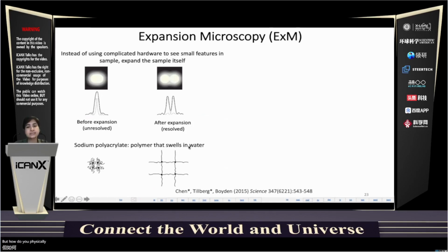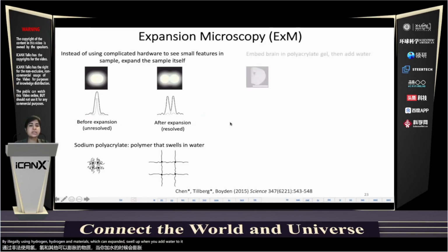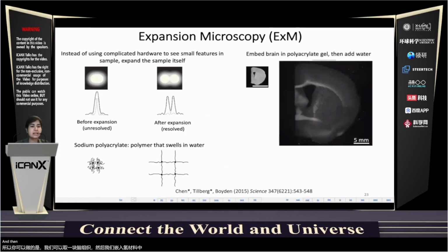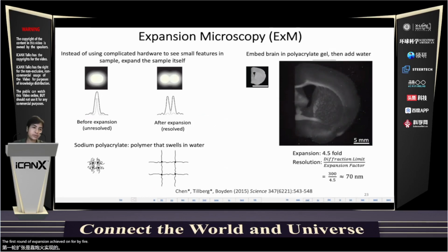But how do we physically expand a sample? You can do that by using hydrogels. Hydrogels are materials which can expand and swell up when you add water to them. So we can take a piece of brain tissue, embed it in the hydrogel material, and then just add water. The brain tissue expands along with the hydrogel. What you're seeing in the image is the same tissue before and after expansion. In the first round of expansion, we achieved around a 4.5-fold expansion factor. That means if the diffraction limit of the microscope is 300 nanometers, by 4.5-fold expansion we can get around 60 to 70 nanometer resolution. With the same hardware, the same diffraction limited microscope, we can overcome this diffraction limit.